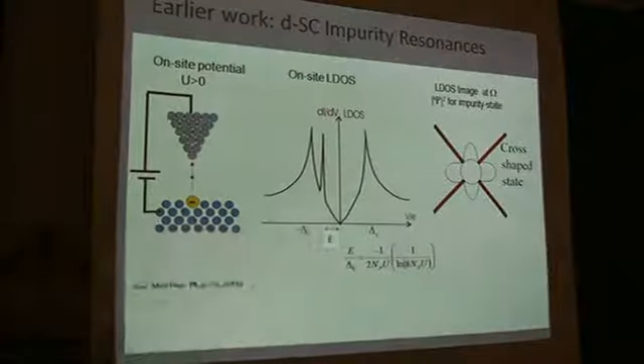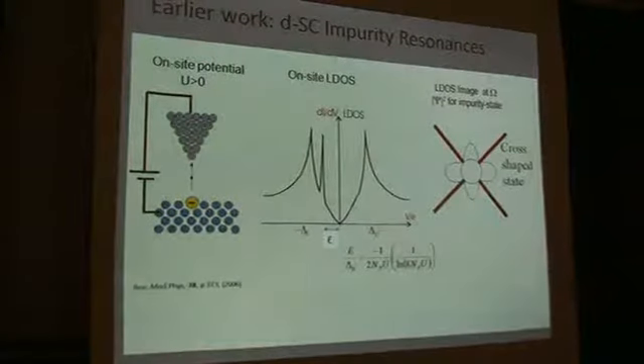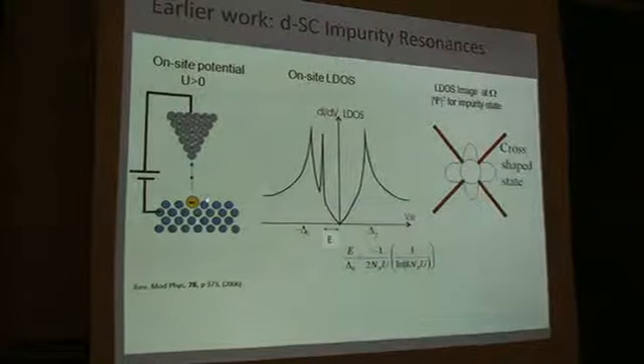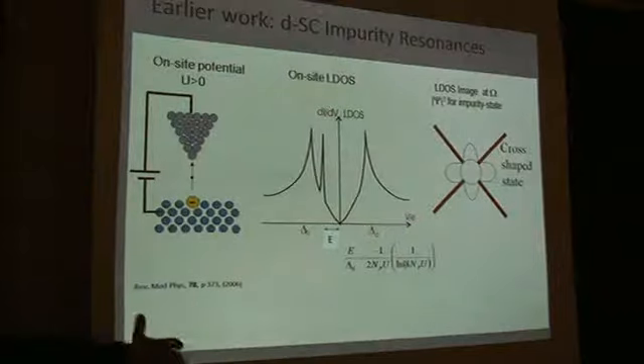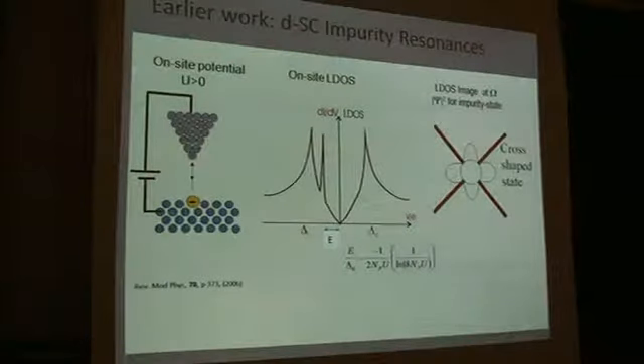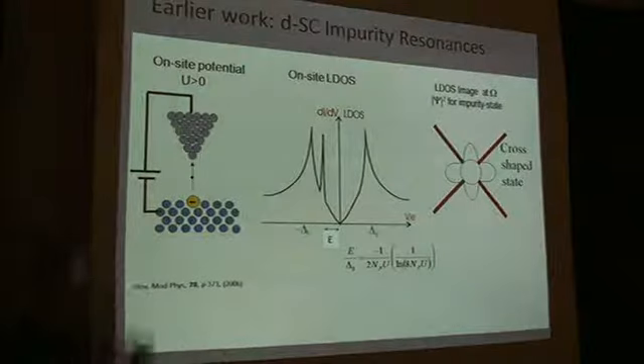Now, one question people were asking early on was: what happens if I put one defect in a superconductor? It's known that superconductivity will be killed, destroyed, if I put defects in, be they magnetic or non-magnetic. But the question is what happens if I have only one? Clearly, one impurity in a cubic meter of superconductor won't do much on average, but locally it can do a lot of damage, right? Because eventually I have to come to the point where the total superconductivity everywhere is killed. The way it's killed is very local. If I put a scalar impurity with potential U here and image locally what the electronic changes are, a couple of things happen. In fact, the same thing happens, but it has a few different features.